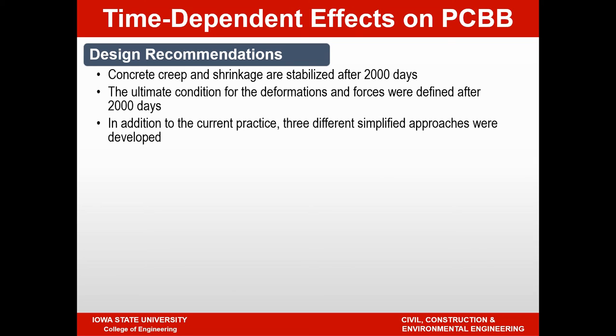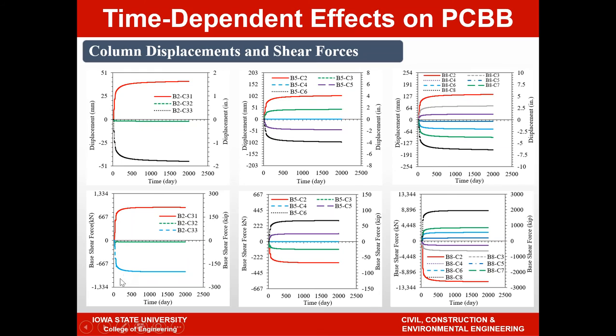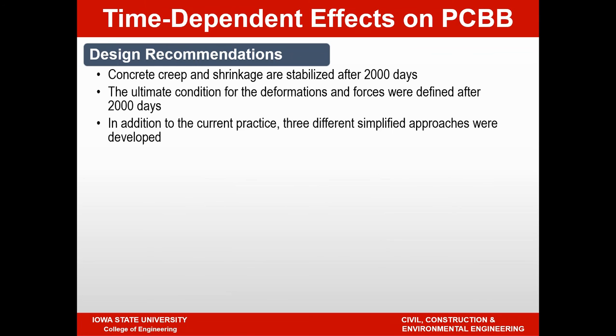So from a design recommendation, what we have done is the concrete creep and shrinkage values are assumed to stabilize after 2,000 days. Even though we picked 2,000 days, I will emphasize, going back to the previous slide, that the amount of time-dependent effect that takes place in a short time frame, something like 6 months, is much more significant, and is probably 80-90% of the total effect that we see in 2,000 days. The reason we use 2,000 days is that it is the number we collectively agreed on with Caltrans as the time by when we assume all of the time-dependent effects have stabilized. So that's the assumption we made.